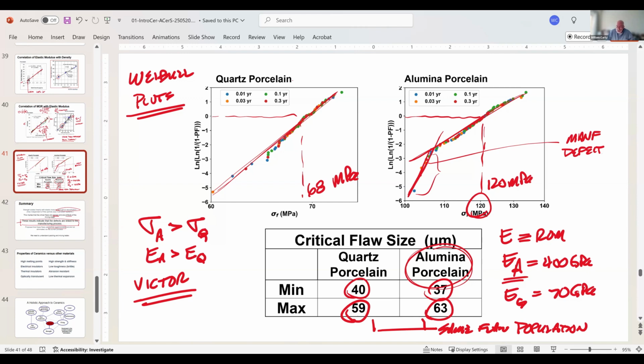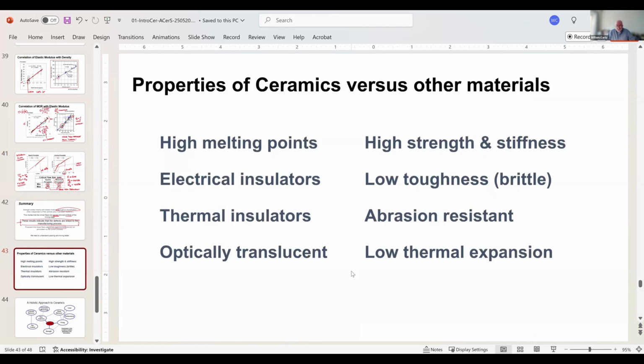Up here, we're fine. And in fact, these two lines don't appear to be the same slope in this plot, but that's because of the x-axis. These are the same slope. So essentially, we have the tools to figure out what's happening in our process, and that comes back to why we generate mechanical testing data and how we use that data in general. I would like to point out that I'm remarkably close on my time.